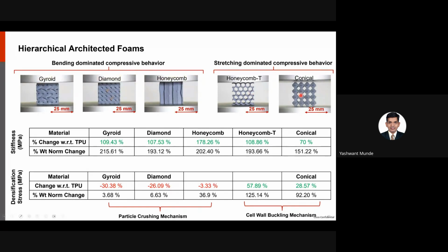Whereas in the stretching dominated ones, which are the tilted honeycomb, key, and conical that I talked about in the first half of my presentation, the key mode of collapse or compression is through buckling of the cell walls, as you can see in these two cases.